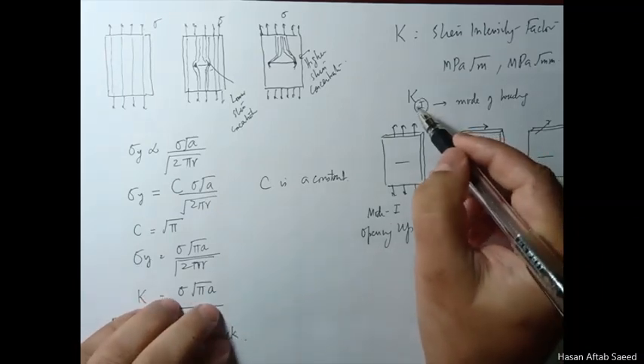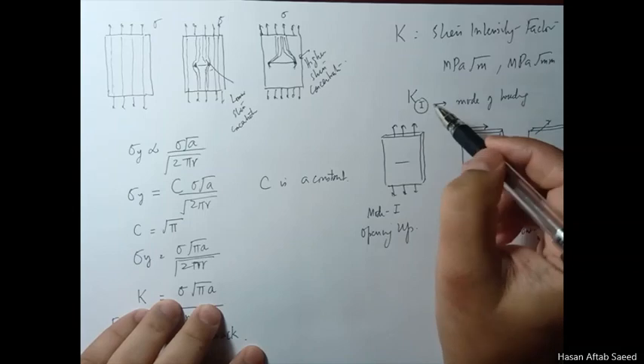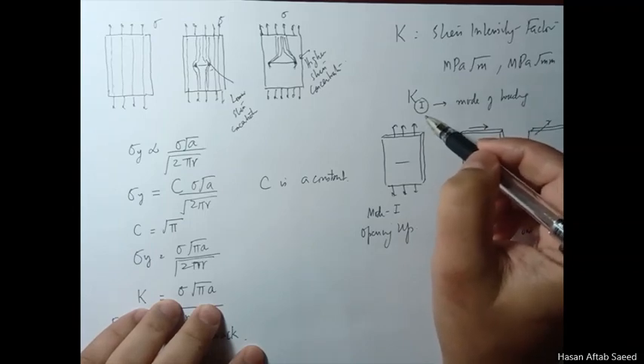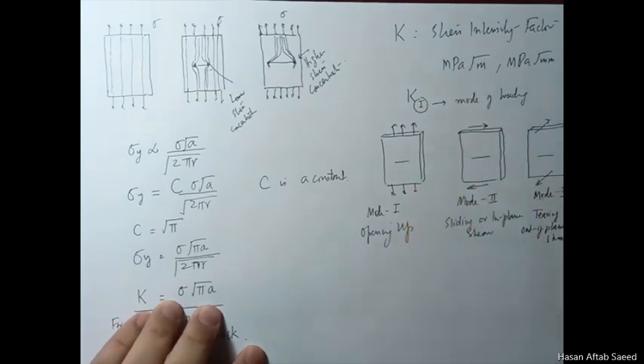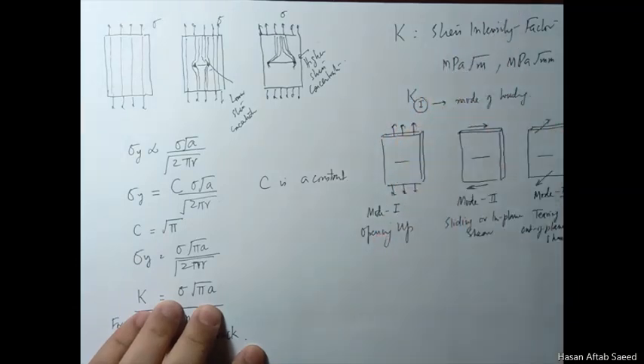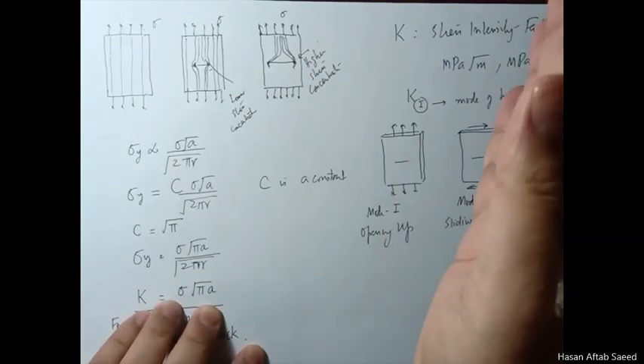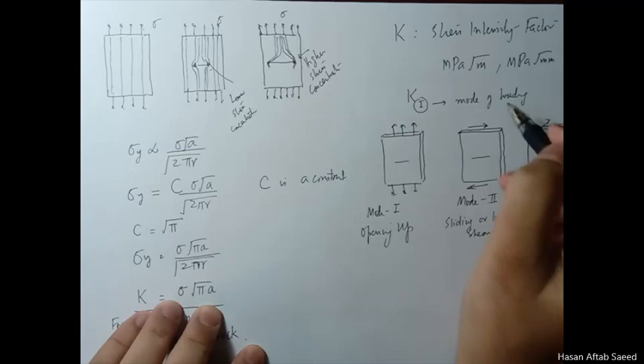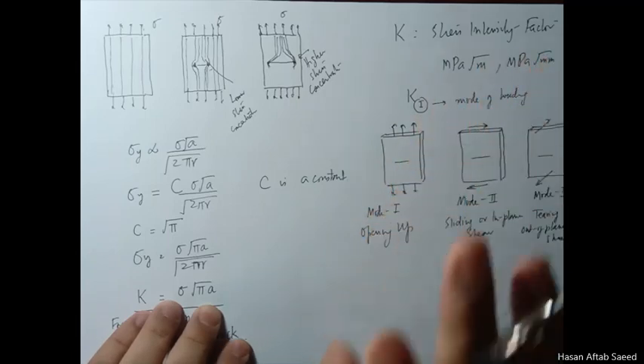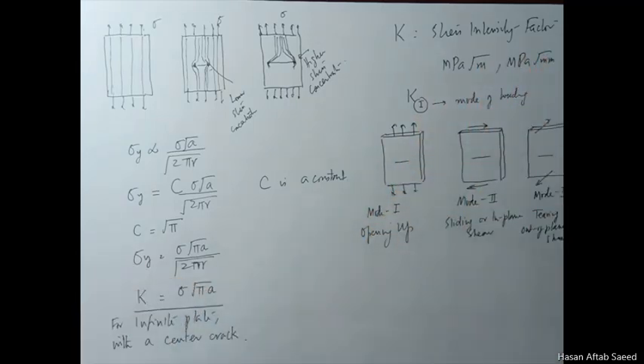So this one only tells you what kind of loading is there. For our purposes in this introductory course, we'll only be dealing with K1, and K1 is the most predominant, most frequently occurring mode. Even in cases where you have mode 2 and mode 3 mixed with K1, ultimately the crack proceeds in such a direction that it becomes K1. So if you can deal with K1 for now, it should be enough.